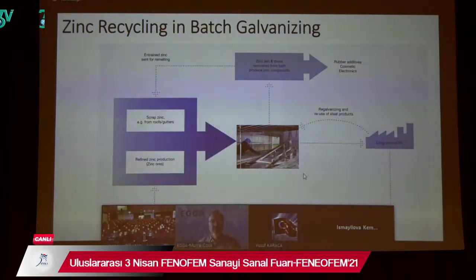But also the ash and the dross, which you see at the top here, there will be some metallic zinc in the ash which comes from the top of the bath, and we can send that also back to the remelting process and use that back in the process.